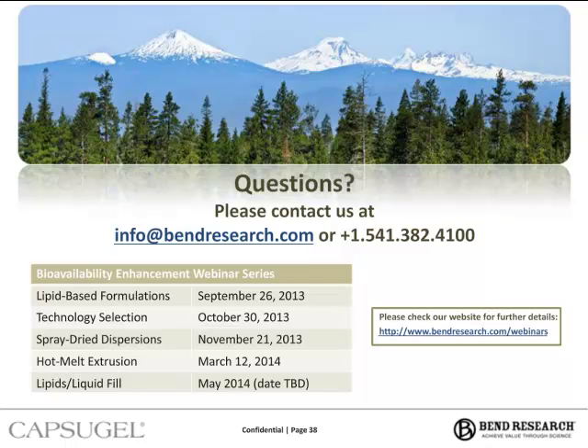Great, thanks. The next question is, do you have any examples of the potential used APIs and with which polymer? So maybe the question is around what type of API are appropriate for which polymer? Right, so in general, we have to characterize the API, and as seen in the presentation, we'll look at the solubility parameters, and a lot of times we'll look at drug-polymer interactions using spectroscopic techniques. Typically the more interaction you see, the better the polymer will work to stabilize the drug in the amorphous form. And maybe something around temperature compatibilities? Yes, relative to the thermal stability of the polymer versus the melting point of the drug, things like that. Great. Thanks, David.